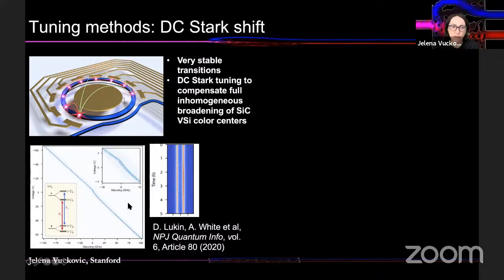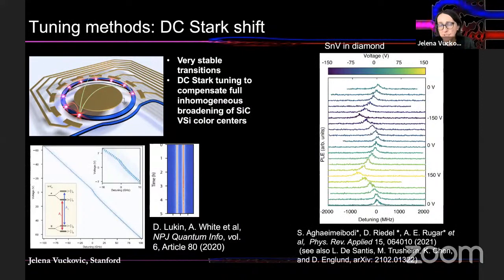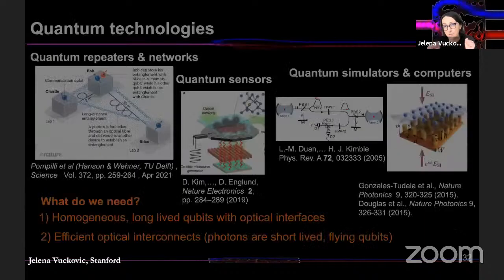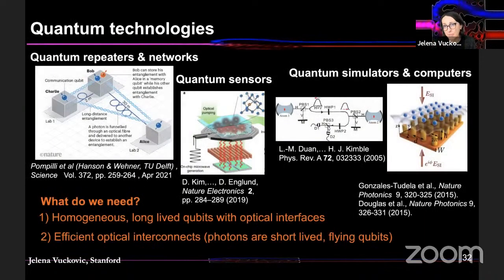And we've shown in silicon carbide that we can do that without degradation to properties of color centers. We can compensate all of the inhomogeneity, and we can also do it in diamond. In diamond, it's a little bit harder because for these color centers there is only quadratic Stark shift, but we can still compensate pretty much all of the inhomogeneities this way. And that's really our tuning knobs. And everybody has tuning knobs.